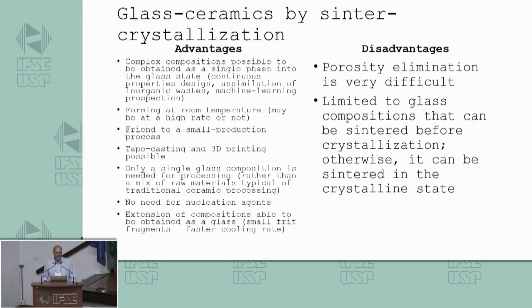And disadvantages are porosity is very difficult to eliminate from this kind of process, either by surface crystallization, or by trapping of gases in the bulk, as Ralph had defined very well. And it's limited to glass compositions, the compositions that are able to form a glass, and also that could sinter before crystallizing. Otherwise, you could not densify using viscous flow sintering. Yeah, you are always able to sinter at higher temperature in the crystalline state by solid state diffusion. But that breaks a little bit what's nice in the system, that could be sintered at lower temperature than traditional ceramics.